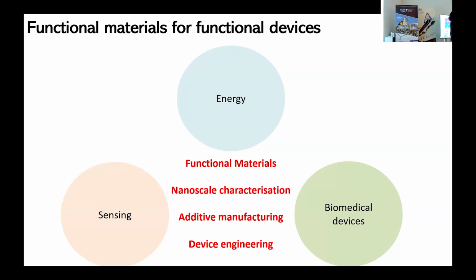So when I say alignment, what we actually have is more texturing along the direction, along the long axis of the pores, right? Because that is the dominant direction along which, one, you have this sort of drawing effect, but two, the way these materials grow is you have nucleation along the walls, and then those grow, and that flow allows more or less alignment along the axis of the pores. But that is not to say that it is a perfect alignment, right? So you will still see the effect from the sides.